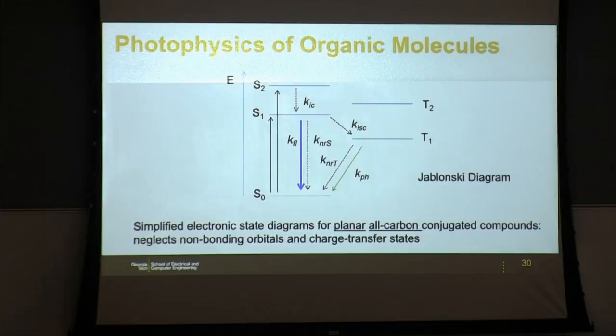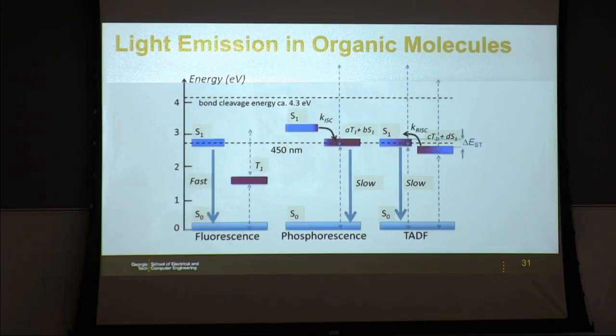Okay? However, you can play tricks, and you can mix some of the singlet and triplet states so that you can partially lift or change that selection rule, or you can play with the energy difference between the singlet and triplet states in order to increase the amount of light emission you can have in these dyes. This was studied as early as the 1930s in isolated molecules, but was only applied to solid-state devices very recently. In the mid-80s, when organic electroluminescence was discovered and applied to thin films, most of the dyes were conventional so-called fluorescent dyes, where you can only have light emission from the singlet states, because light emission from the triplet states is forbidden. Okay, so that limits you to 25% efficiency.